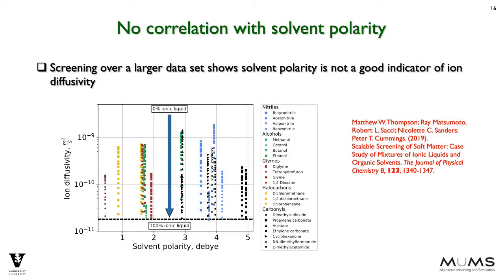With this much larger data set, how does diffusivity depending on solvent polarity look, as we concluded from the more limited experimental and MD study? This figure suggests there is no correlation with solvent dipole moment. In this figure, the BMIM diffusivity is plotted as a function of solvent polarity. Each vertical line of points corresponds to a solvent and the points to different compositions. That is, each line contains 18 points, ranging from the lowest concentration at the top to neat ionic liquid at the bottom, which is shown as a dashed line.